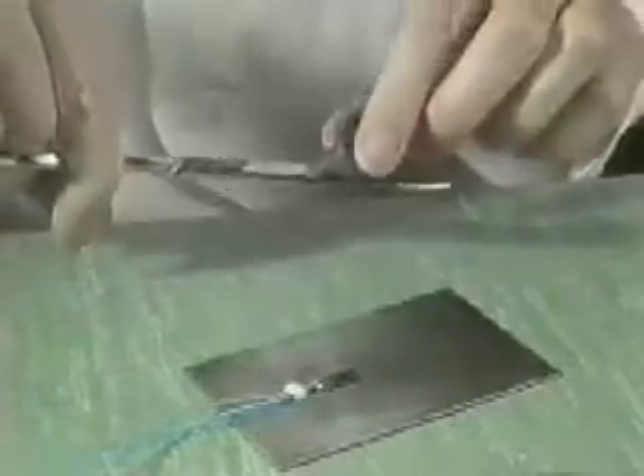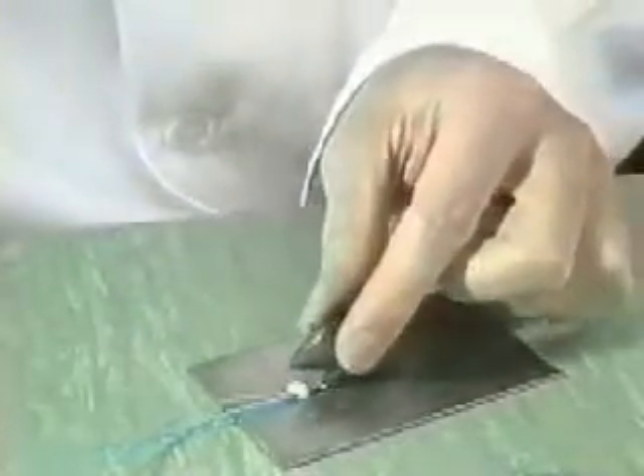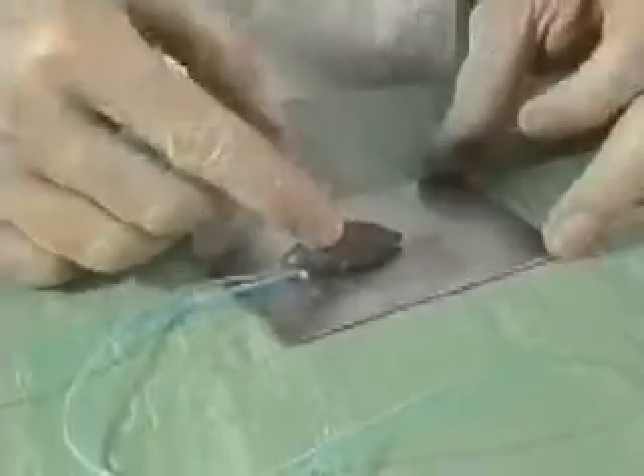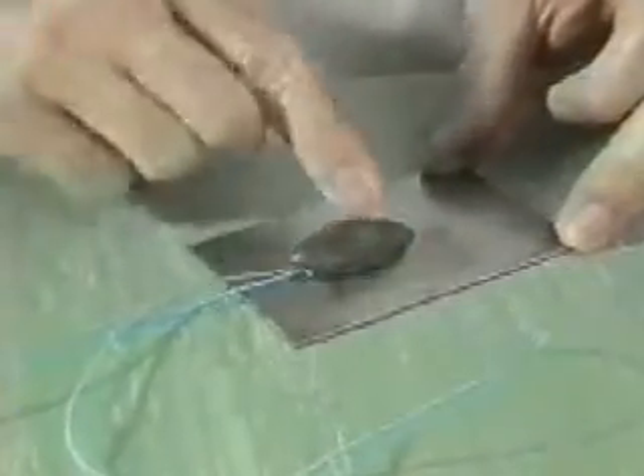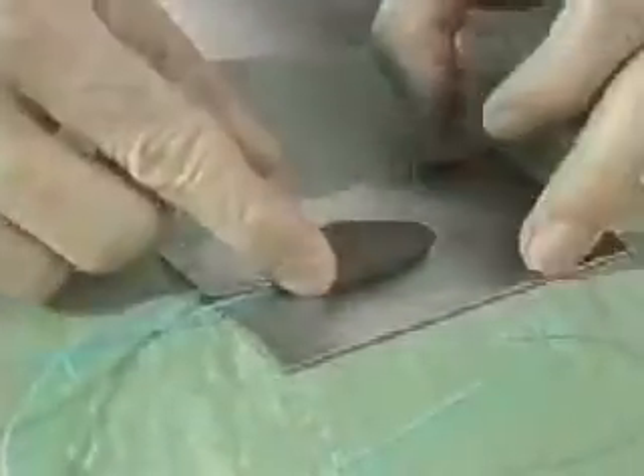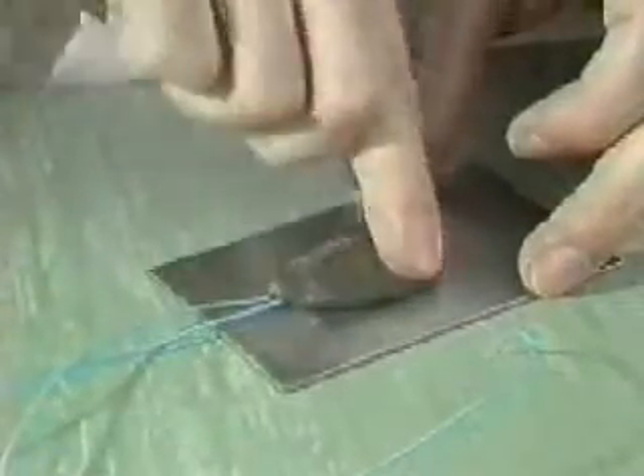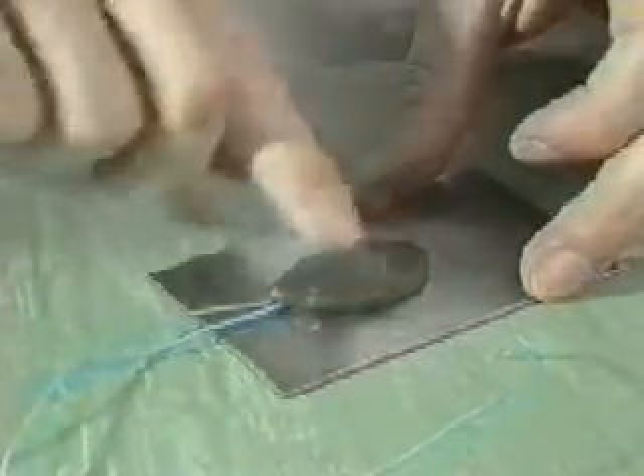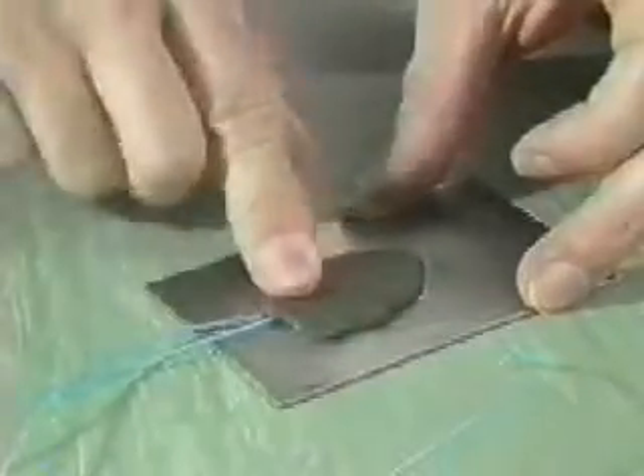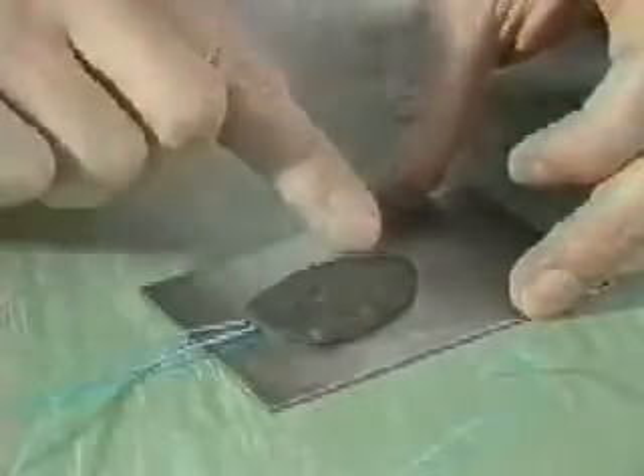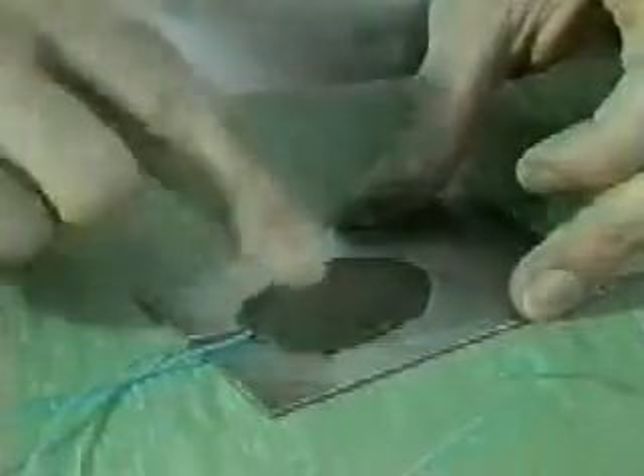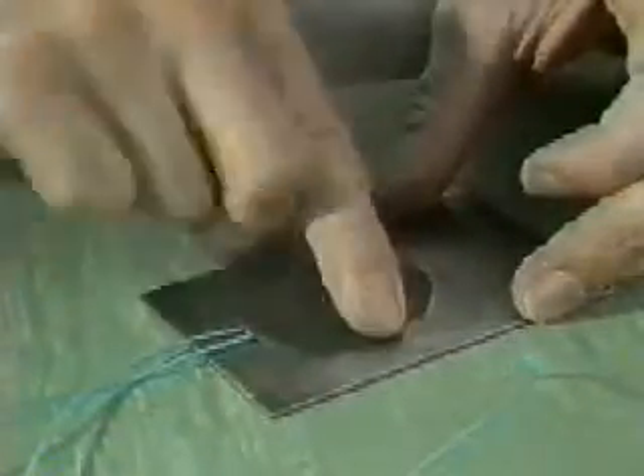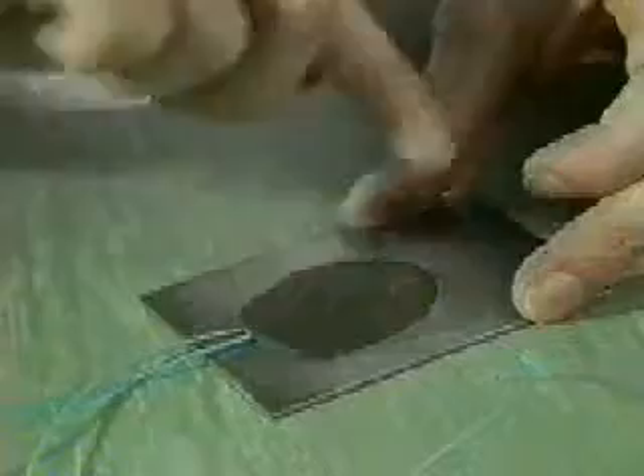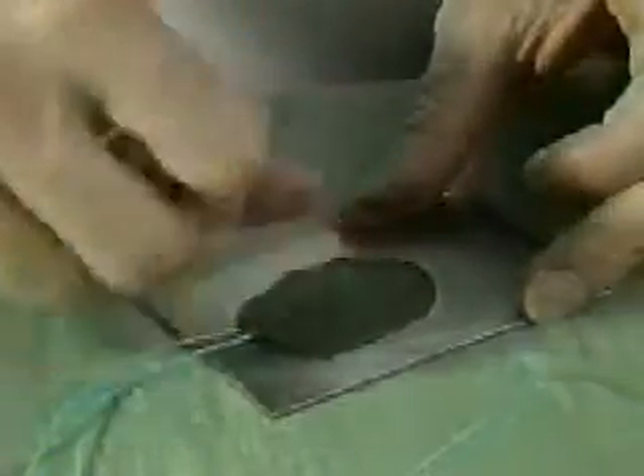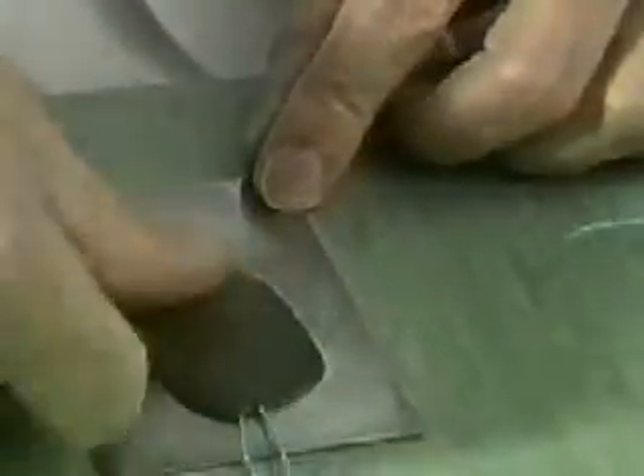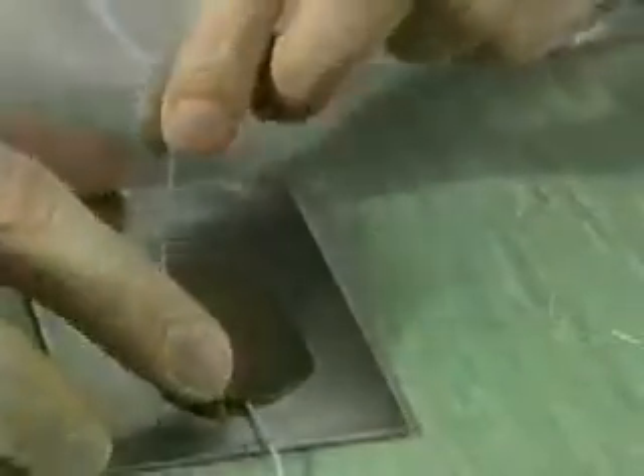A small piece of AK22 is placed with the cut surface on the strain gauge and firmly kneaded, starting from the center. Only use the fingertips for kneading. Grooves pressed in by the fingernails are detrimental to the covering. After a short period, the putty adheres to the sheeting so well that solvent would have to be used to completely remove it. The cores of the lead are pressed into this layer.